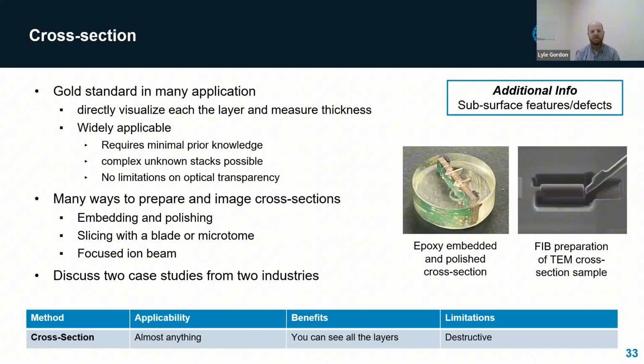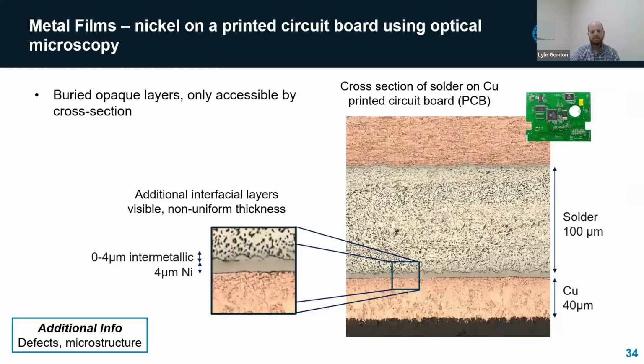So this is really widely used, but another limitation here is that you can't really practically map the thickness over a lot of areas. You'll have to just pick a few spots where you prepare the cross sections. So here we have this application of a cross section. In this case, it's a printed circuit board.